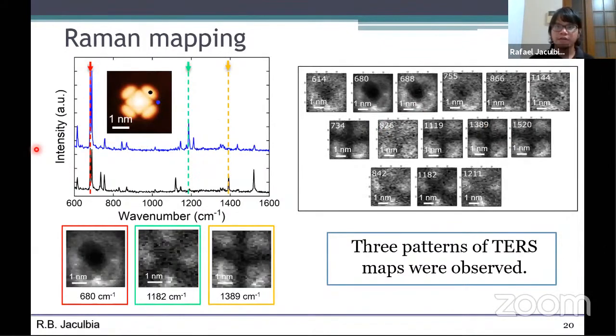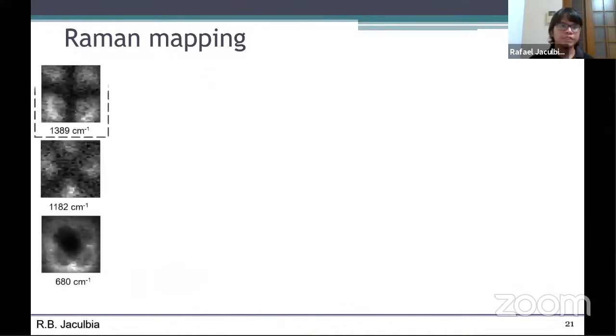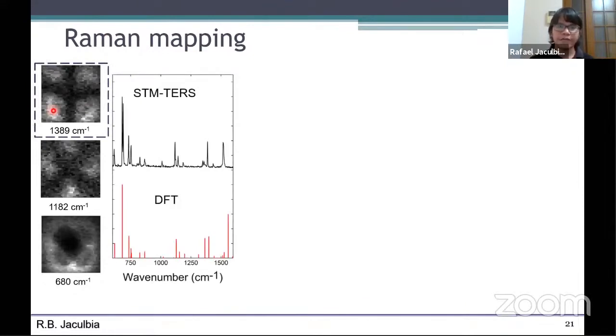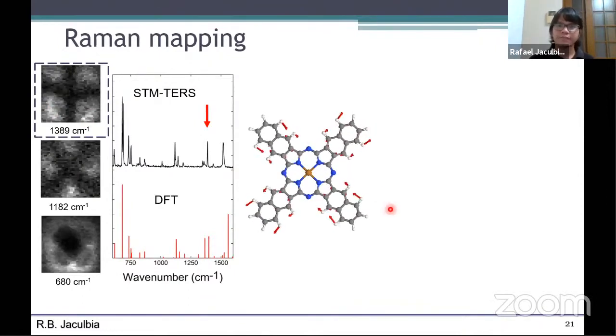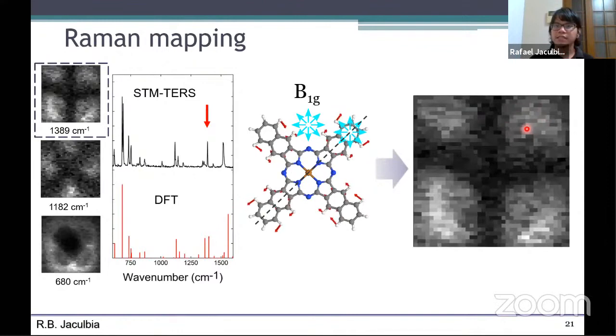In order to see how this happens, for example, this 1389 mode, by comparing with the DFT calculations, we found that this mode has these vibrations. Our explanation is that this mode has a symmetry of B1g. When we place the tip along this symmetry axis, for example here, these 2 modes are vibrating in phase. But when the tip is placed here, modes here and modes here are vibrating out of phase. So we propose that when the tip is here, this mode is enhanced, and when the tip is here, these modes are canceled. That's why the shape is like this: enhanced signal here, and reduced signal here, here, here, and at the center.